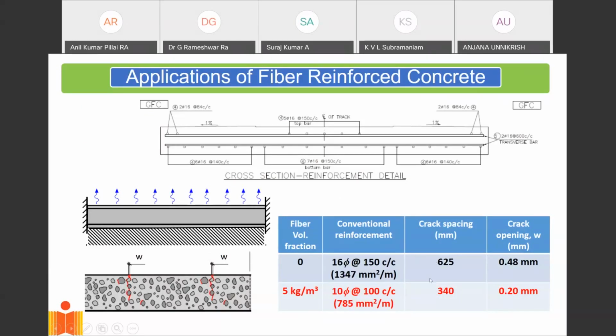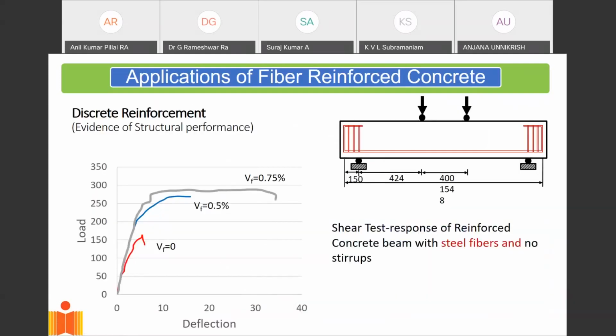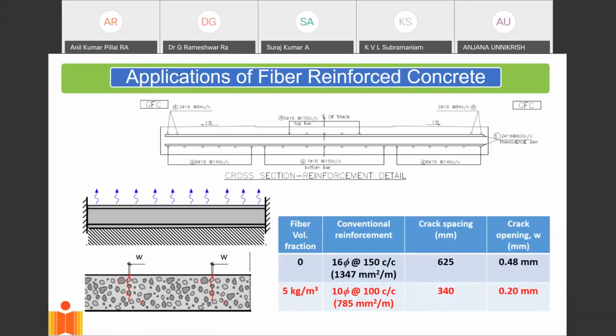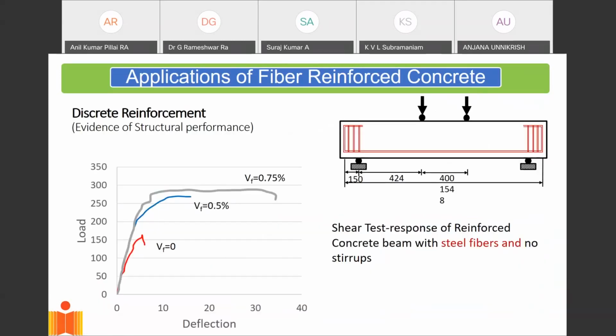At the same time, without compromising the crack opening, we achieved a crack opening of 0.2 mm, which is within the norms of serviceability requirement specified in the Indian code. So these are essentially the applications of fibers, which up to this point have been non-structural. But now fibers are also coming mainstream in structural applications, where if I add fiber to concrete, we look at improvement in the shear performance of concrete.